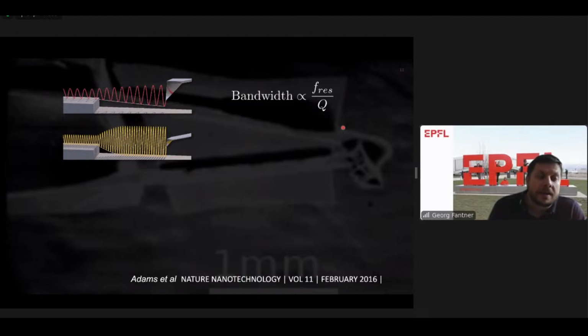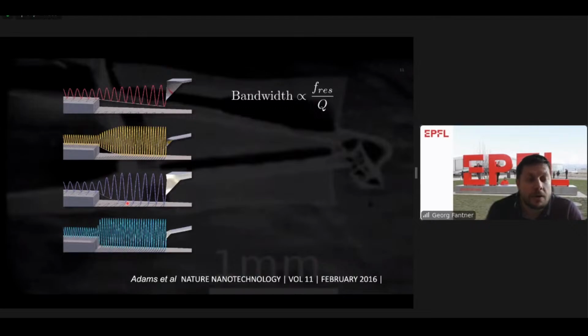So in theory, if we could control this Q, then we could also achieve a high bandwidth by keeping the resonance frequency constant. So we could make potentially a cantilever that has the same resonance frequency, but a lower Q factor, and we would get the same speed with which we detect the topography. And ideally, of course, we would do both. We would make a very small cantilever that has a low Q factor, and therefore would only require very few cycles to find the new steady state, but at the same time go through those cycles very quickly.